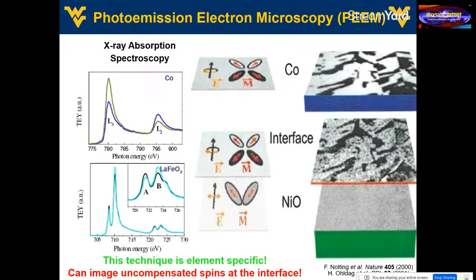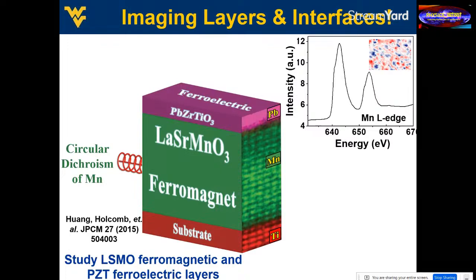So here's an example. This is another one. So cobalt still on the surface. Now we have nickel oxide that is buried underneath, which is also an antiferromagnet. But if you use circularly polarized light on the nickel edge, you can image the interface between these two materials and actually look at the uncompensated spin at purely the interface. So we wanted to do exactly the same thing in our case of magnetoelectrics.